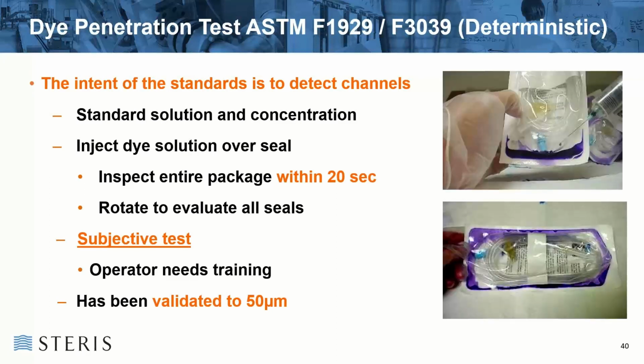So typically what you're seeing here in both pictures is the dye being introduced into the actual packaging. That's method A in ASTM F1929, where the dye is injected into the actual pouch, and you'll see that it's actually trying to leach out and wick out through the actual seal.